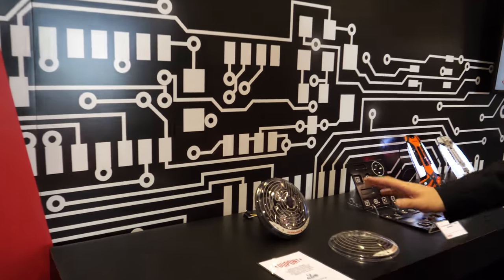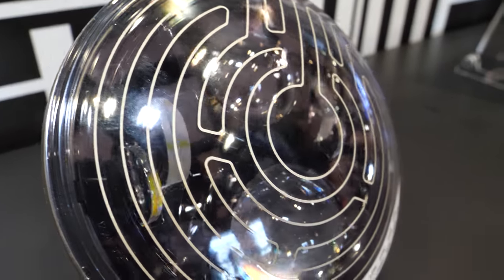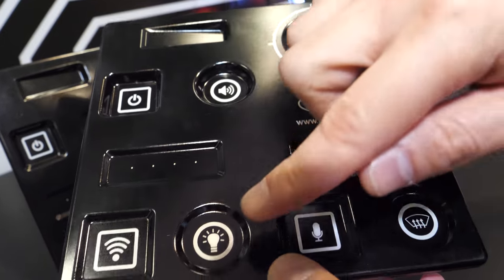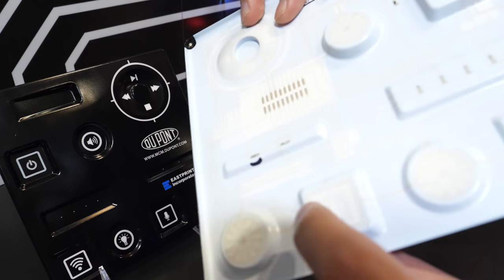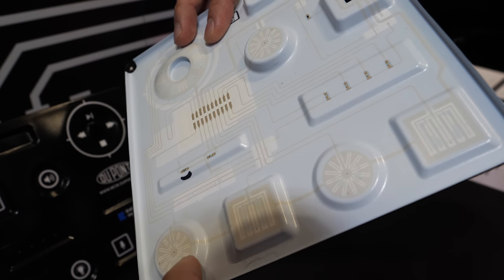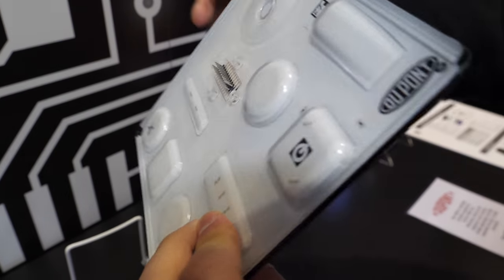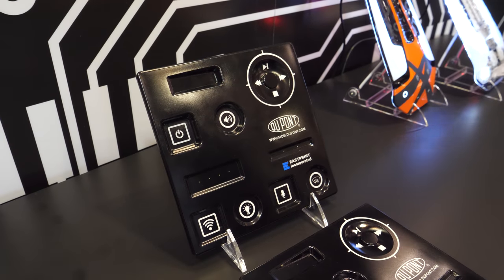Right here we're looking more at in-mold electronics. If you think about a 2D screen printing technology and then thermal forming into a 3D shape, the throughput is high because we're printing 2D and then creating different types of stretching elongation. The conductive ink and dielectric ink can be stretched to a 3D form, and then we do injection molding to give the structure with a single connector to plug in. The assembly time will be very fast.